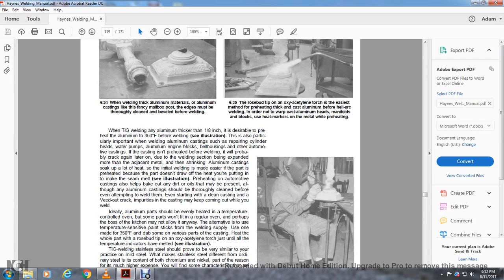Alright, when TIG welding any aluminum thicker than 1/8 of an inch, you want to preheat the aluminum to 350 degrees before welding. This is also particularly important when welding aluminum castings, such as cylinder heads, water pumps, aluminum engine blocks, bell housings, and other automotive part castings. If the casting isn't preheated before welding, there's a probability it will crack later on